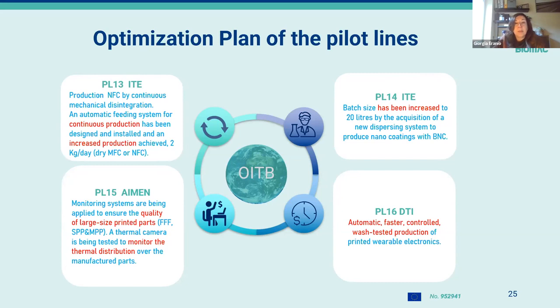Always by the same partner, pilot line 14 increased the batch size up to 20 liters by the acquisition of a new dispersing system to produce nano coatings with BNC. And then pilot line 15 managed to install a monitoring system to ensure the quality of large size printed parts through photopolymerization and fused filament production. And then a thermal camera has been installed and tested to monitor the thermal distribution over manufactured parts. Pilot line 16 by DTI managed to ensure an automatic, faster control wash test production of printed wearable electronics.